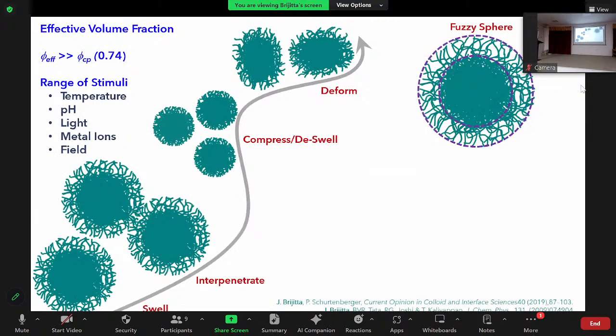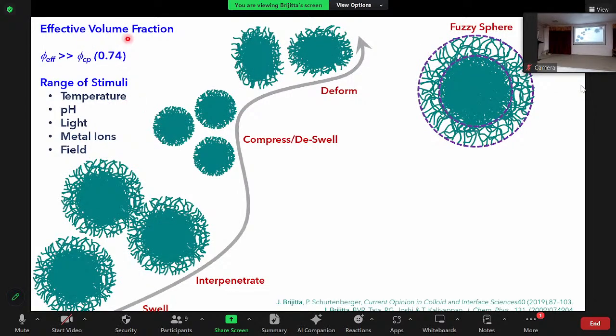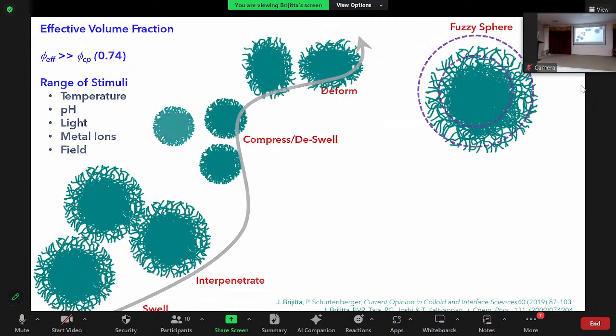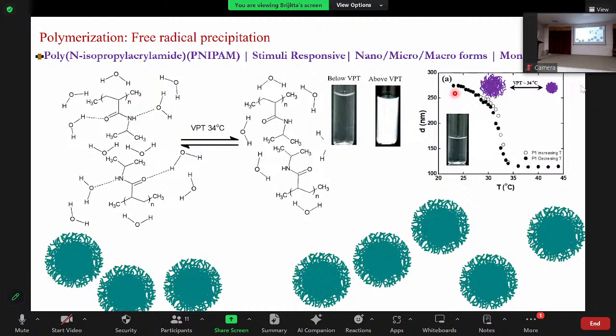So now once you have this system, what can you do with it? You know that in hard spheres, for example, as most of you have studied in solid state physics or solid state chemistry, the maximum packing fraction possible, that is the volume fraction, is 0.74. But these systems of gels which I am showing you here are quite different from those systems, because you can go beyond the maximum close packing of 0.74. This is because the size is changing with temperature. In any hard sphere system, for example, if you take polystyrene spheres or gold atoms, the gold size doesn't change with temperature. So for every temperature, it's going to be the same gold atom size. It is not going to change size.